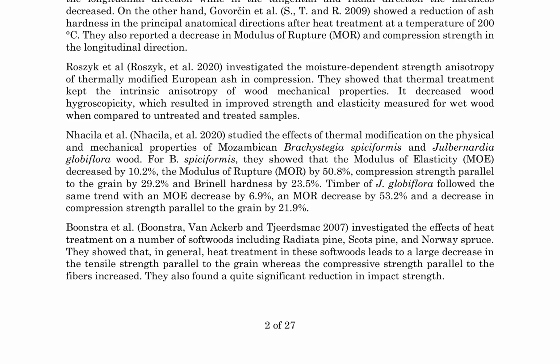Heat treatment has also been applied to softwoods, including radiata pine, Scots pine, and Norway spruce, resulting in a large decrease in tensile strength parallel to the grain, an increase in compressive strength parallel to the fibers, and a significant reduction in impact strength. These findings collectively highlight the complex effects of thermal modification on wood mechanical properties, emphasizing the need for further research to fully understand its implications.